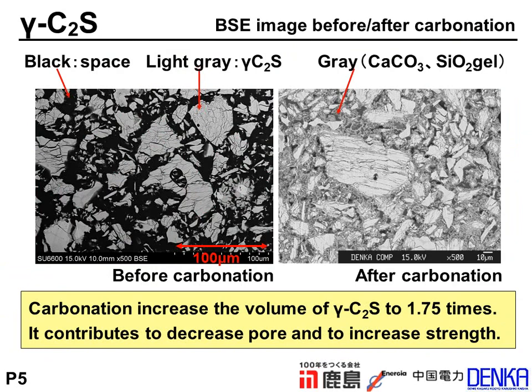And the gray substance consists of calcium carbonate and silicon dioxide gel. So carbonation increased the volume of gamma C2S to 1.75 times theoretically. So it contributes to decreasing the pores and increasing the strength.